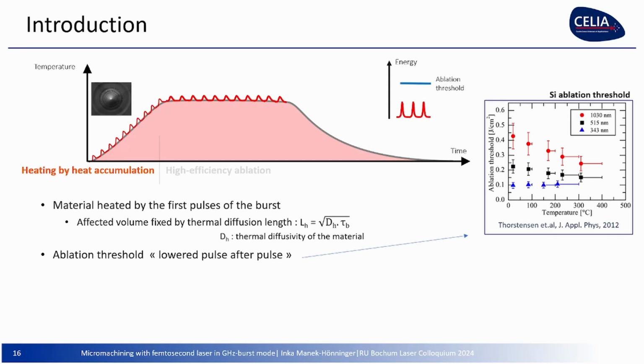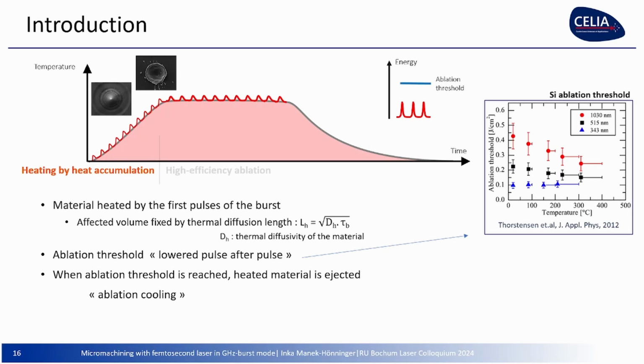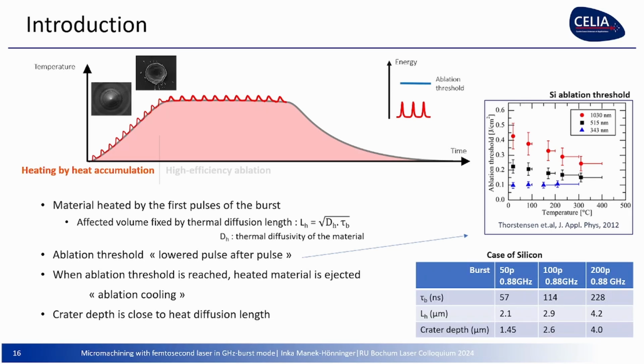And then, when you reach the ablation threshold, the heated material is ejected. This is what Oehmer called ablation cooling, because the ablated matter takes away lots of the heat. Of course, there's some residual heat, but not much. This is what we call ablation cooling, and the crater depth that we observe is really related to the heat diffusion length.